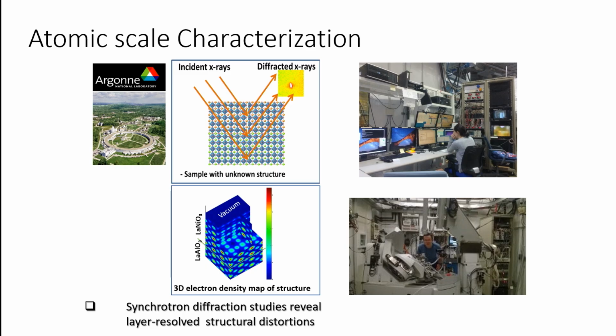And the technique that my group specializes in allows us to get diffraction data in 3 dimensions for films which are epitaxial with a substrate. Being able to go back from the diffraction data to a real space image is pretty challenging. But we use a technique which allows us to do that, to reconstruct the diffraction data into real space 3-dimensional electron density distribution maps of our systems.